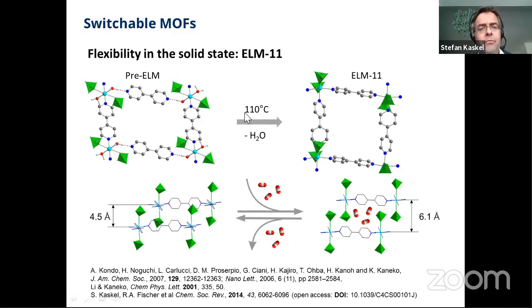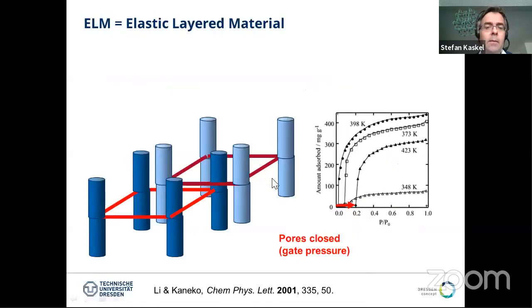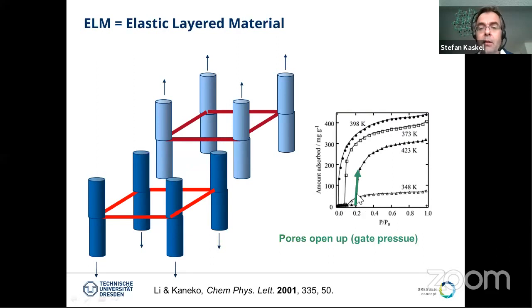And this structure looks a bit complicated, so there's a very simplified way to look at this. So we can see this is the square net here, and I draw the BF4 minus anion just as a rod. And this rod is blocking the pore when the system is closed. And in the isotherm here from the original paper in 2001, we see that there's no adsorption up to a certain pressure, 0.2. And at this pressure, suddenly the pore pops open, and there's a very high uptake, and it continues like this.